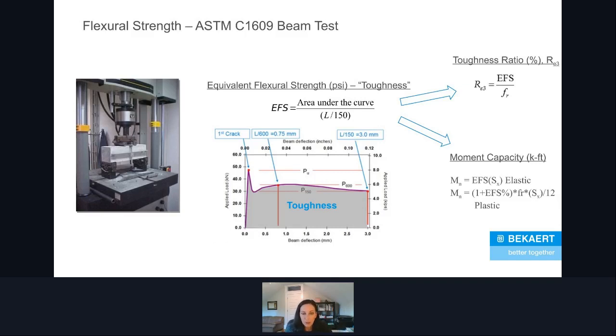If you integrate under this curve, you're going to get a value known as toughness. This is from ACI 360, which is a slab on ground design guide. And if you take that toughness and average it out, divide it by the L/150 value, you'll get a value known as the EFS, the equivalent flexural strength. That's a value in PSI. And so if you have an EFS of 200 PSI, 300 PSI, whatever the case might be, now you have an actual performance metric to use as you compare to other solutions. Again, this is a categorization of the post-crack flexural performance of this SFRC.